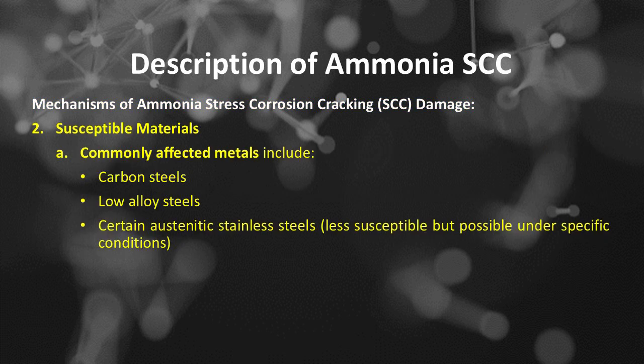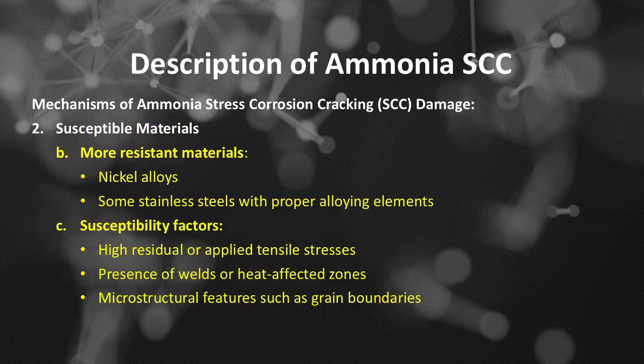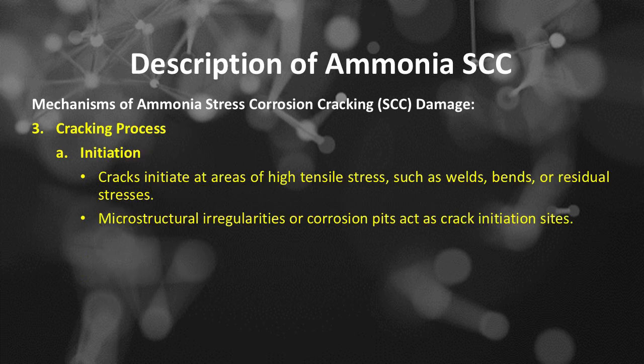Number 2 is susceptible materials. Number A, commonly affected metals include carbon steels, low alloy steels, and certain austenitic stainless steels, which are less susceptible but possible under specific conditions. Number B, more resistant materials include nickel alloys and some stainless steels with proper alloying elements. Number C, susceptibility factors: high residual or applied tensile stresses, presence of welds or heat-affected zones, microstructural features such as grain boundaries.